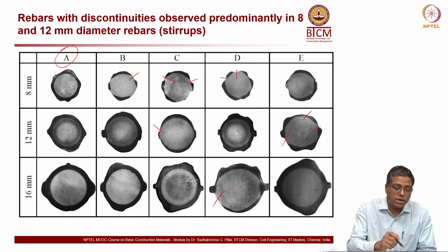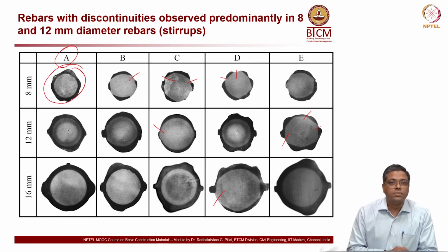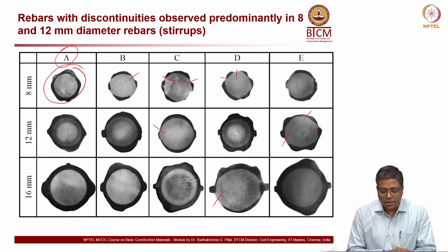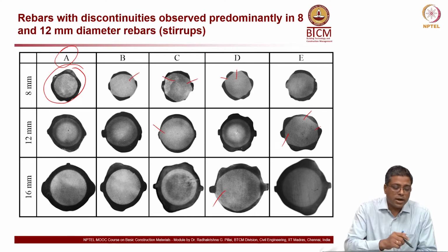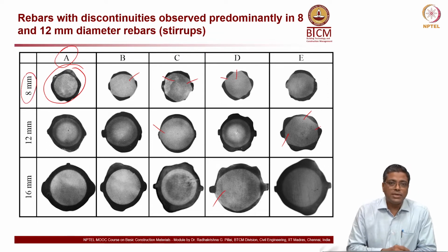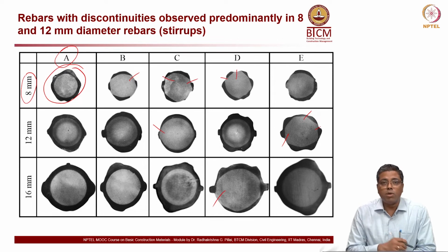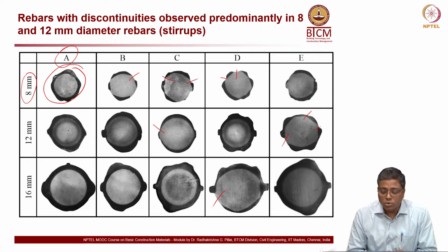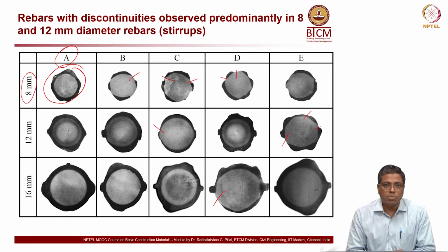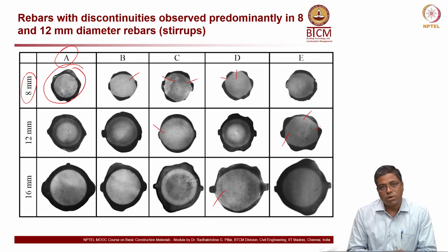So for a good quality rebar, you need something like this. Full ring is required. And one more thing to note, in this picture itself, if you see, the smaller diameter bar on the top row, 8 mm, is having more problem than the larger diameter bar. So if you ask a manufacturer and do this TMT ring test, they will actually do it on a larger diameter bar, and you may not be able to capture the problem.